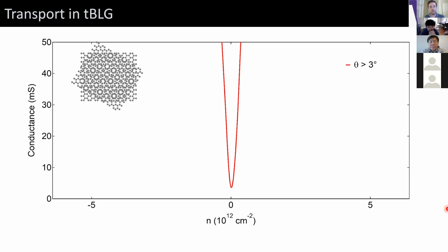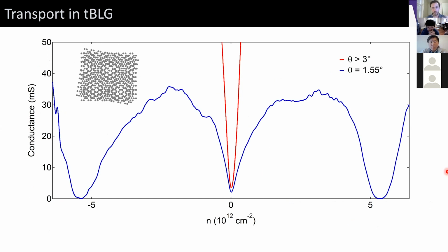Well, if the twist angle is large, then it basically looks like 2 sheets of monolayer graphene measured in parallel. So for above 3 degrees, the conductance of the sheet is low at the neutrality point, and then it grows as we dope the system with more electrons or more holes. But if we make the twist angle smaller now and the Moiré pattern grows bigger, then something distinct happens as we start to dope with more electrons or more holes. The conductance eventually saturates and then drops to identically 0 before recovering to some finite value again. And this is roughly particle-hole symmetric.